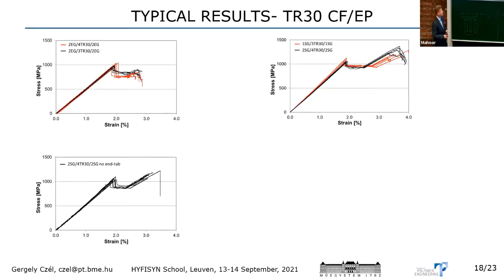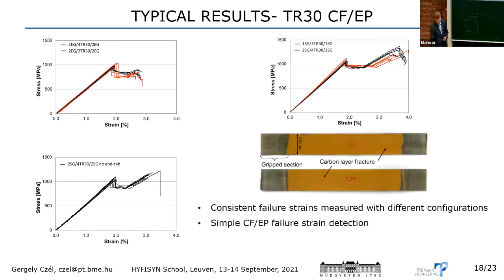And what we get as a result is these type of graphs with a clear load drop, and this corresponds to the failure strain of the carbon epoxy layer. And this slide is designed to show that we had 5 different configurations, even with E-glass protective layers, and then S-glass protective layers, different number of carbon fibers of the same type, with and without end tabs, and we've got consistently the same failure strain for the same carbon epoxy material. And yes, it was quite simple to determine the strains at which the carbon epoxy failed just by looking at the test graphs.